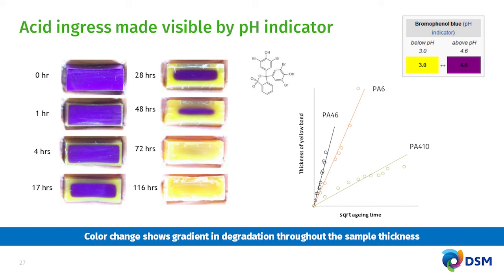And something that we also observe is that wherever there is a yellow layer, there is also typically a low molar mass of the polymer, and also a crack starts to be formed, and also pretty brittle materials that we observe when there is a yellow layer band on there.